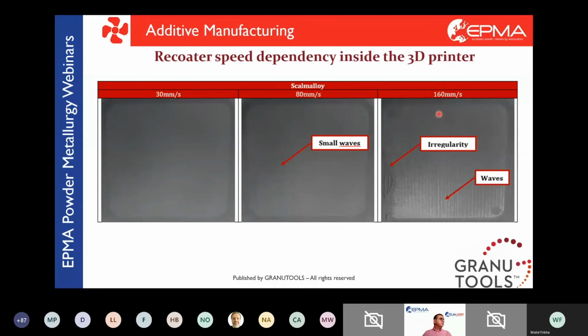And what we do is inside the printer, we are taking pictures from the top. We can see that at 30 millimeters per second, we have a quite regular powder layer. At 80 millimeters per second, we start to have small waves. And at 160 millimeters per second, we have irregularities and big waves.